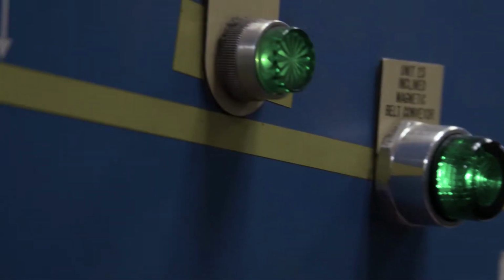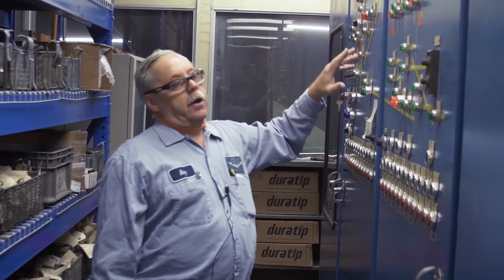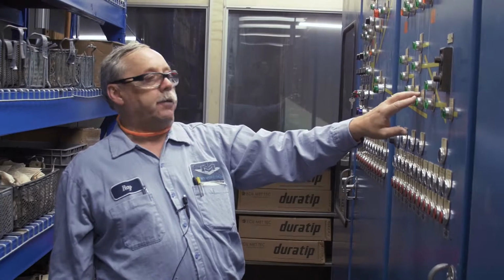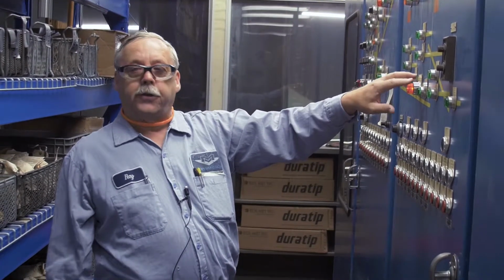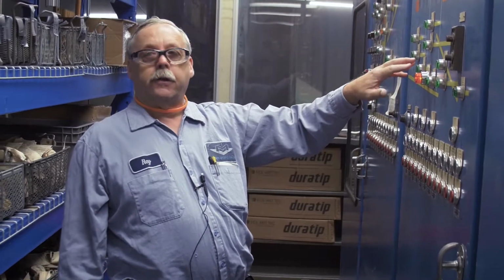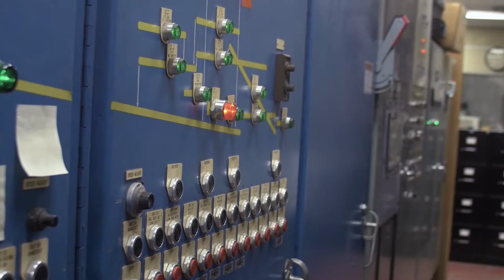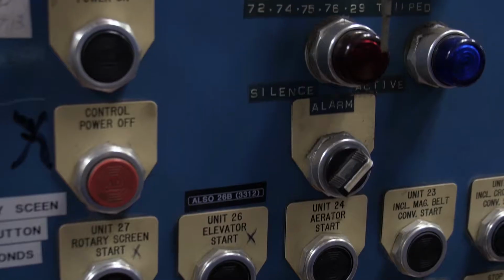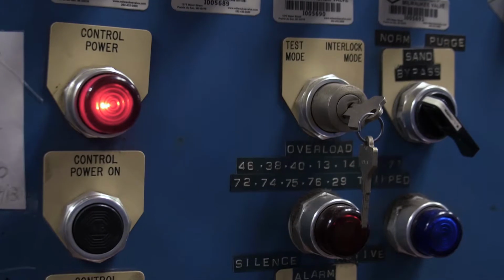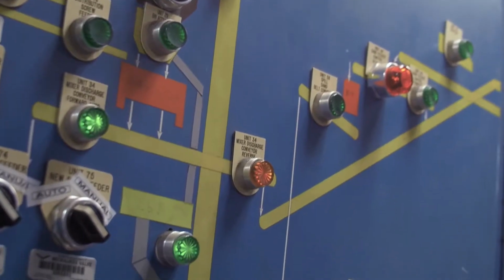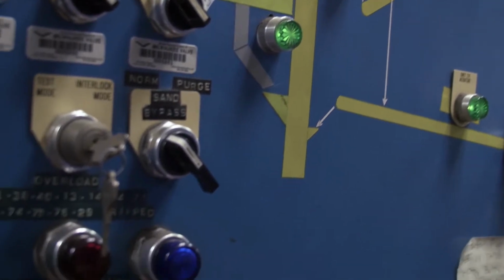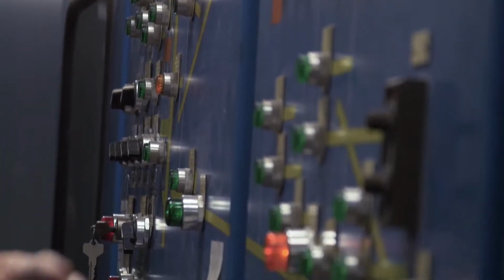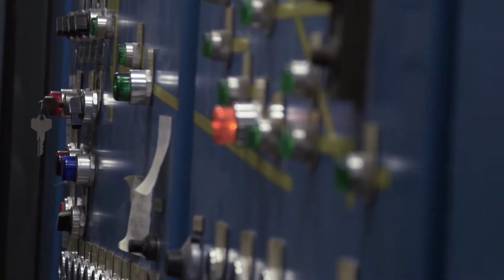There's probes on it. If I draw a line through here, this would be our base floor. We got spill sand conveyors and shakeouts below floor, and the shakeouts are in the dirtiest, noisiest part of a foundry, which we separated. Nobody has to work in that area on a regular basis. The castings and runners and sprues and everything comes out in the basement. The sand meanwhile goes back up this conveyor, goes into a bucket elevator, and we screen out any core butts and fine metallics after that. Any conveyor that shuts down will shut down the whole system that feeds it and behind it, and it'll shut down our molding line so we don't bury anything in the sand. We have zero speed controls on all of it.